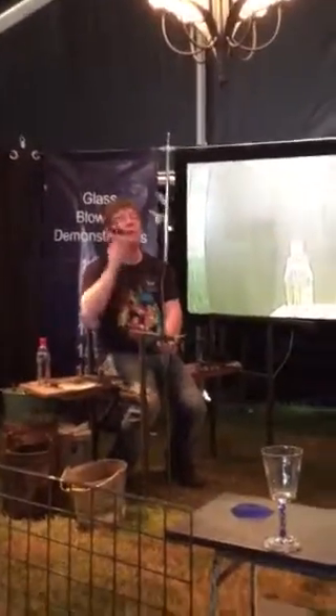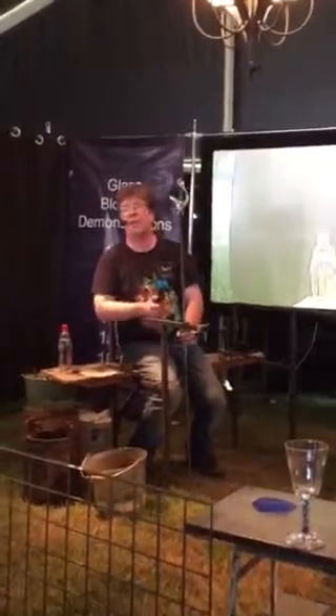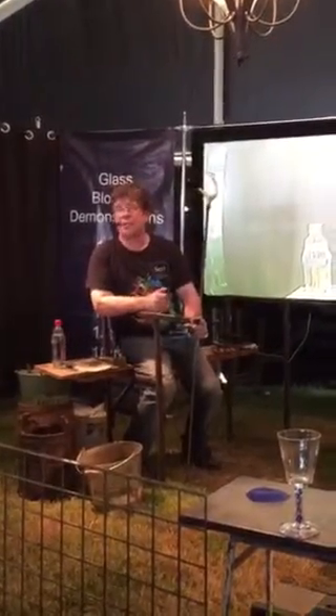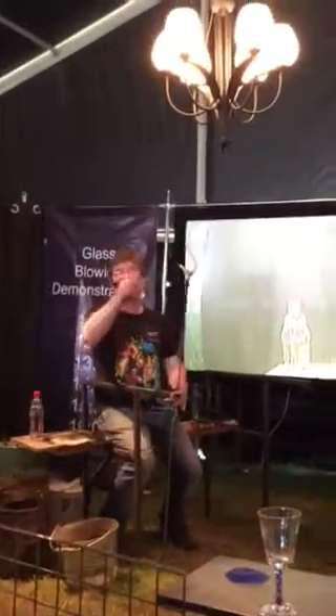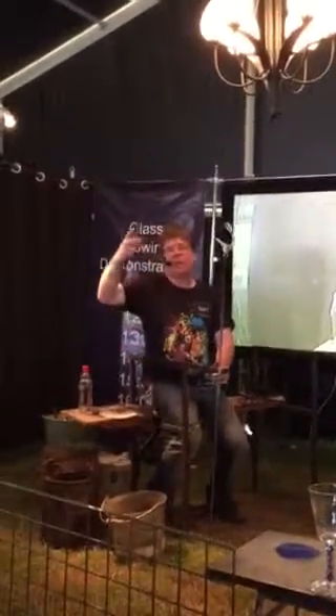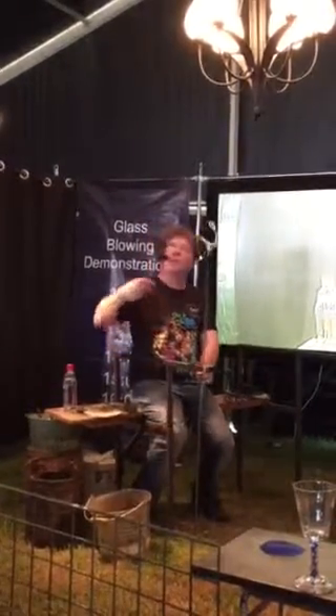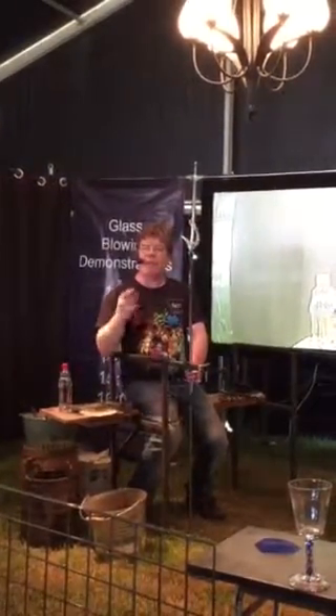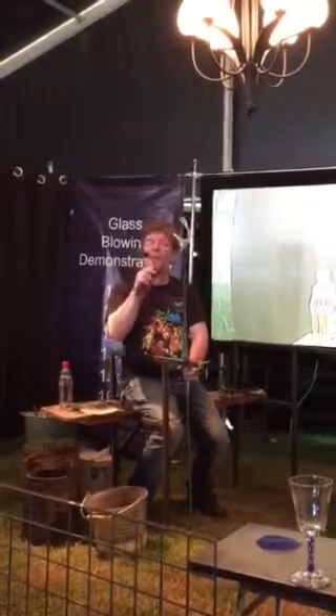And once it's set in place, we've got a huge amount of technical problems. Because from now on, as it continues to cool, it actually starts to shrink, but it doesn't shrink evenly. It starts to shrink from the outside inwards because the outside's in the cold air. So it starts to squeeze all the hot glass on the inside because the outside shrinks first. And the pressure builds and builds and builds to such an extent that this will explode in about 10 minutes' time.